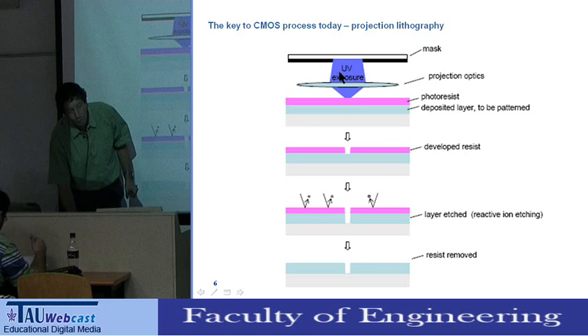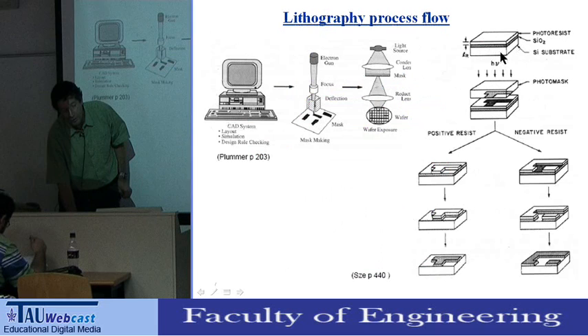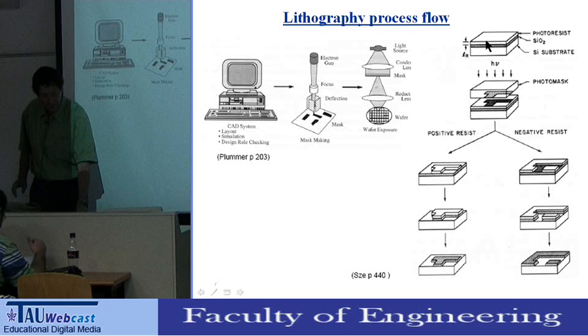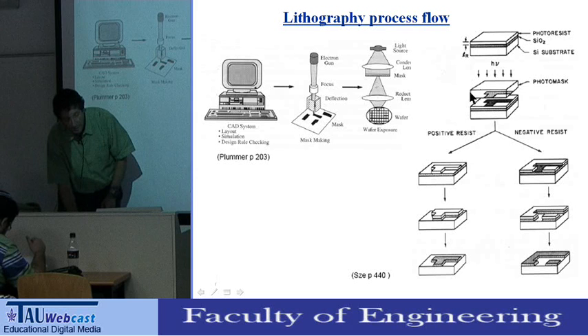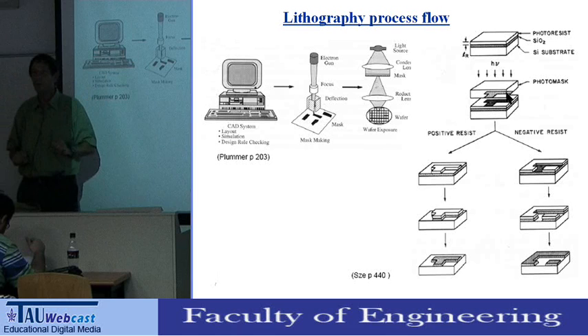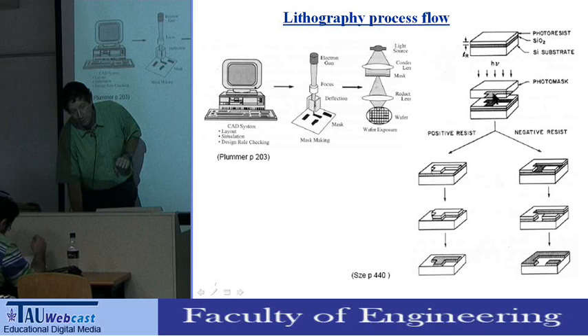Now, projection lithography, for example, for silicon, we take a silicon substrate. On the substrate, we put silicon dioxide. And then on top of it, we put photoresist. Next, we put the mask. If you look at this mask, the mask is made of a transparent material. But here, in this area, we put a shape, like an L-shaped structure made of opaque metal. It's made of chromium, a very thin layer of chromium. So if we illuminate this structure, this area is shadowed, this area is not.